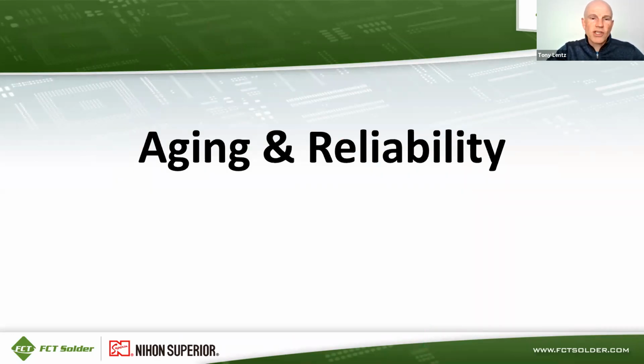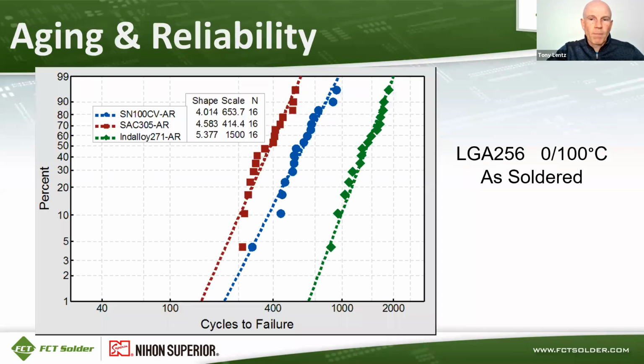Here's some data on aging and reliability. So this is an LGA 256 that was thermal cycled from 0 to 100C as soldered. And you can see the green diamonds are Indalloy 271, and that had the longest life, followed by SN100CV, which is in the middle, and SAC305, which is to the left. Those are the red squares.